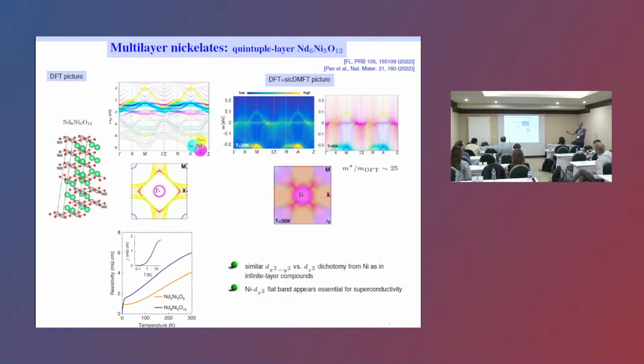And we also see that different theories give very good agreement in some parts and maybe worse agreement in other parts. And this is also from cuprates. I mean, some theories give super agreement for some measurements and completely fail for other measurements and vice versa. And we just have to select out and find if there's a common concept that one theory can cover all. And we also have to be careful if we have super good agreement, like in my case with this photoemission, or in Carsten's case with the dome, just from one experiment or from one probe, claiming that this is now the perfect theory, because there could be accidental agreements which could lead you on the wrong track. So with this, I would like to finish and open for questions. Thank you.